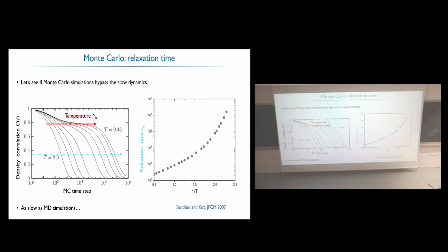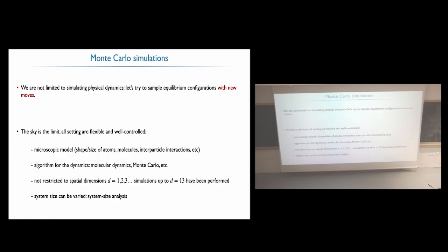So let's look again at what happens when you use this kind of dynamics. Well, you start to know the story now. If you look at the density correlation, basically the time scale increases. And again, if you look at the relaxation time as a function of 1/T, now the time is expressed in Monte Carlo steps, but whatever, you see exactly the same shape, and then you also become dead at around 10 to the 6, so it means that you cannot really go below what you could do with molecular dynamics.